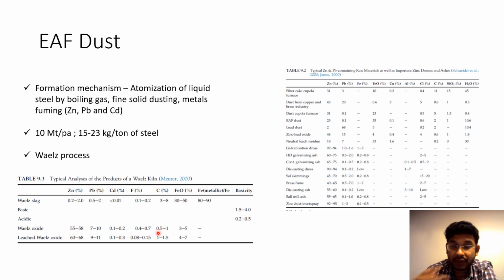Herein, I already gave away the most important bottleneck in handling EAF dust and the need to go beyond the Waelz process, because to handle halogens is not so easy, because eventually you have to fight with zinc, because all these things are also going to end up in dust or fines or in these vaporization chambers in one way or the other. Of course, you can sequentially try to remove it, and even if it ends up in the dust or the end product of an oxide, you can try to wash it off, but the presence of halogen is an impediment to this sort of pyrometallurgical process, and we will see how we can tackle it.